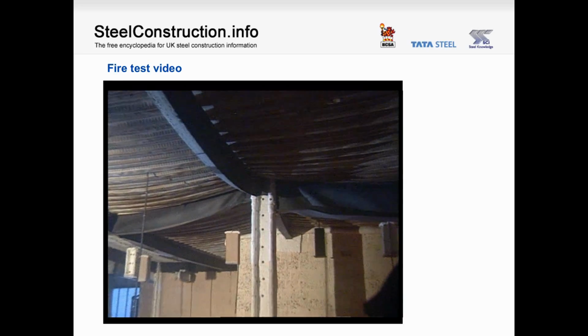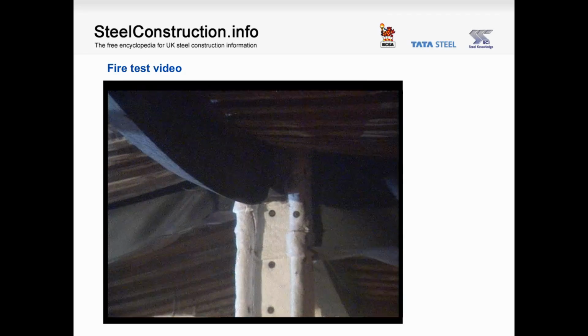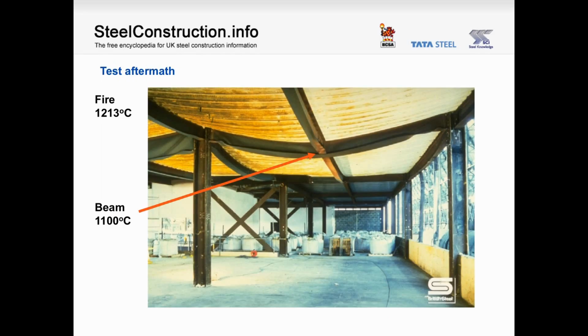And here you're looking at the aftermath. We are looking at beams which are bent and distorted, but on which there has been no collapse. This is the aftermath of the office fire test when everything had been cleared up. The beams deflected significantly, about 1100 millimeters on a 9.5 meter span at the maximum, and this retracted to about 700 millimeters on cooling. But the floors remained intact. The beam survived a temperature of 1100 degrees centigrade. A standard isolated beam of this size in a fire test loaded to the same level as the Cardington frame would have failed at about 700 degrees centigrade.